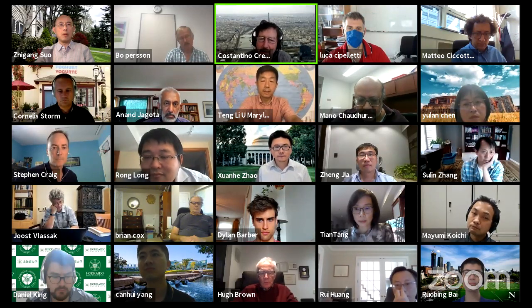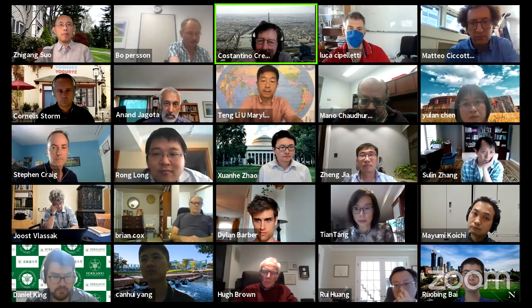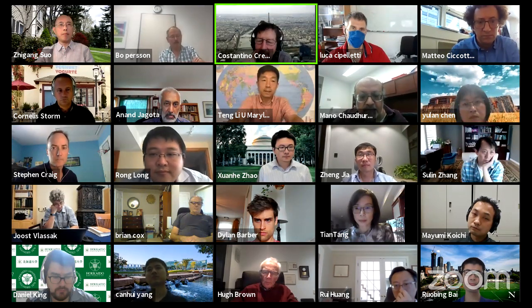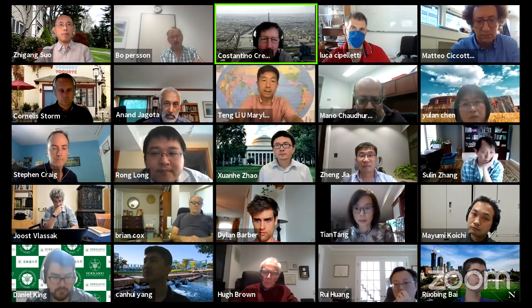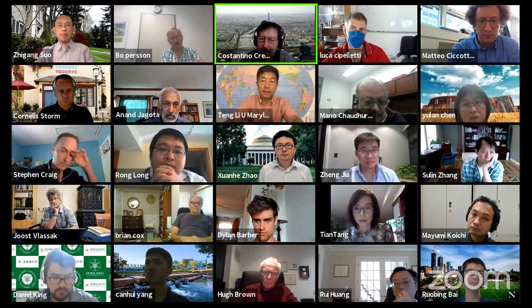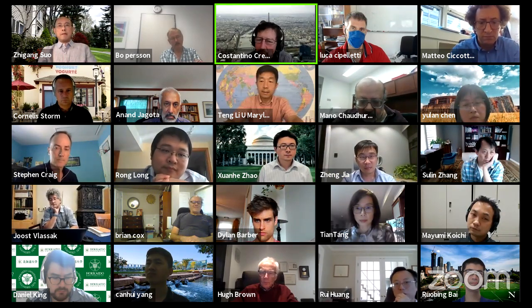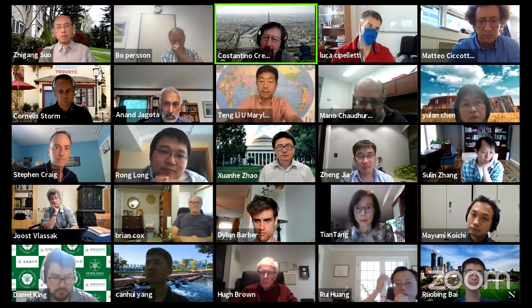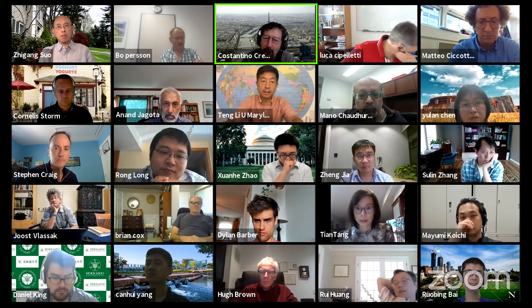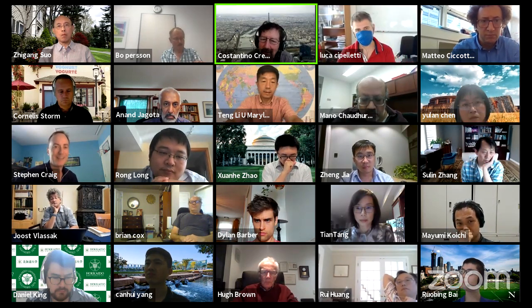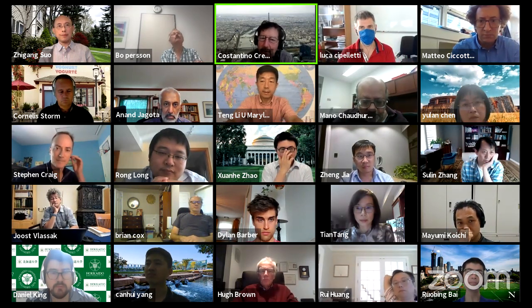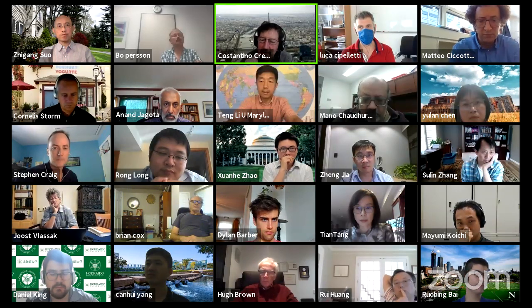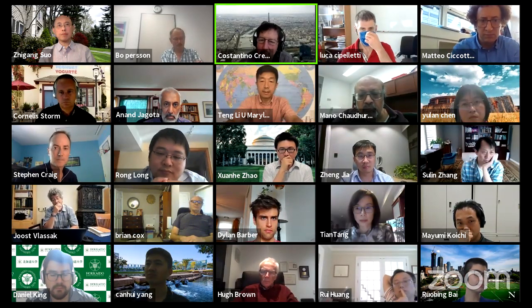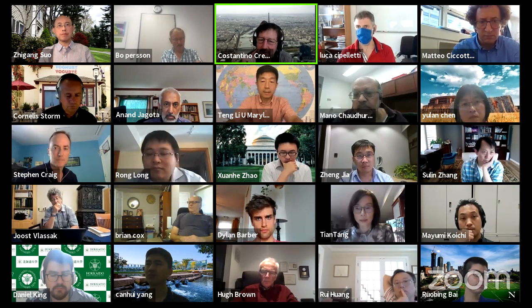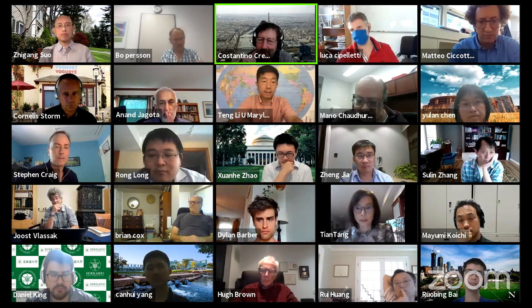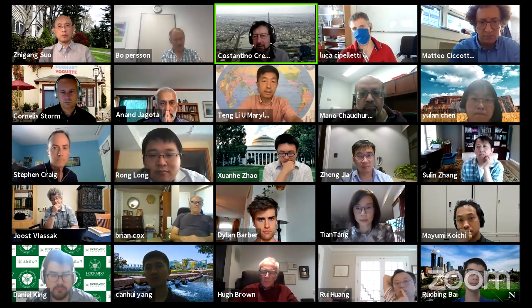But looking directly at the tip of the crack, Zhigang was right, these macroscopic properties are pretty reproducible. It's not an issue of that, but on the other hand, each crack is different. So if you want to do measurement at that small length scale, you have to think what's the relevant way, how do I average things properly? And so there is, I think, an experimental difficulty.